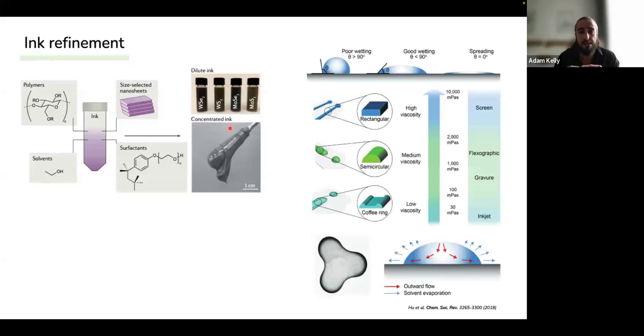So the properties of these inks are very well understood because inks have been around for a long time. The properties that are important to us are, in particular, the wetting. We would like to have wetting that forms networks in a way where the droplets form continuous networks, for example. Depending on the viscosity of the ink, the deposited droplets will form different shapes, and the viscosity needs to be very well tuned to the deposition process itself. Now, when you're working with dilute inks, like the inkjet printed inks up here, we get problems with droplet evaporation.